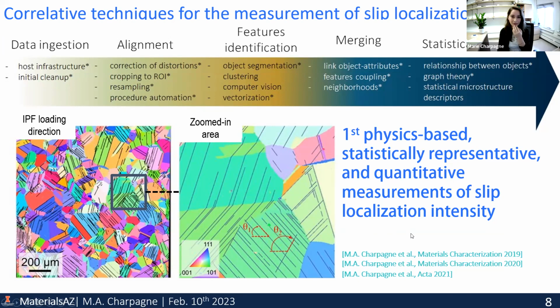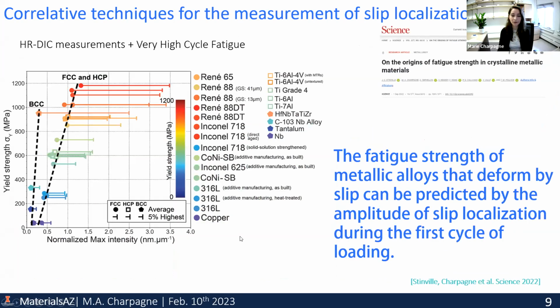And so with this, we have a very robust framework where we can really statistically investigate the slip localization intensity, meaning the intensity of those slip bands as a function of the microstructure in pretty much any material. So the whole workflow is very robust, and we've collected many data sets. The major finding with this framework, given that we had so many materials, was published recently in a high impact journal, where we found that the fatigue strength of any metallic alloy that deforms by this process of dislocation slip can actually be predicted by the amplitude of slip localization during the very first loading cycle.